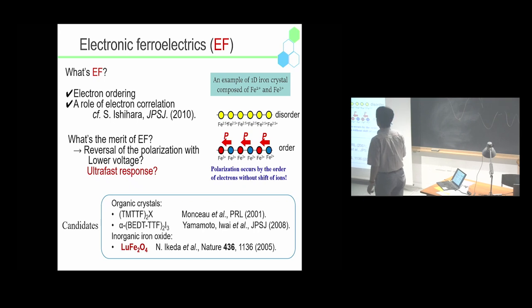Here's an example of a one-dimensional iron crystal composed of Fe2+ and Fe3+. If the electrons are itinerant, you can see no polarization, because all the iron cations take 2.5+. However, if some ordering of the Fe3+ and Fe2+ occurs, you can see an arrangement of the polarization P. Then the polarization occurs by the ordering of the electrons without shift of any ions. This is a typical schematic to explain the electronic ferroelectrics. Of course, in electronic ferroelectrics, the role of electron correlation is quite important, as Professor Ishihara proposed in 2010.